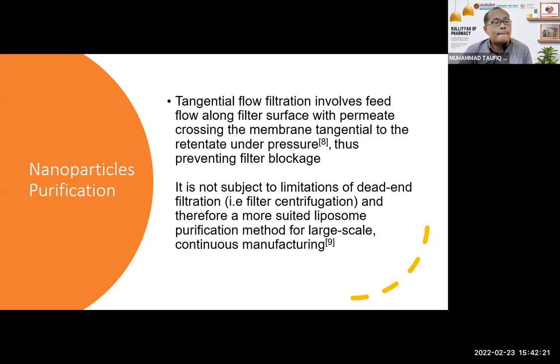Then we come to the purification. If we talk about purification of nanoparticles, the usual way that we do this is through centrifugation. You can go for high-speed centrifugation, where you achieve tens of thousands of Gs in order to have the pellet and the supernatant, and then you remove the supernatant and wash it again. But I found that usually these kinds of methods are very stressful to the liposomes. Remember that the liposome is almost like a cell without the cytoskeleton. So if you put it under so much pressure, it will just flatten. It's not a very strong structure.